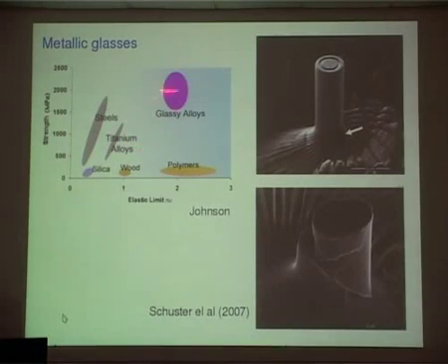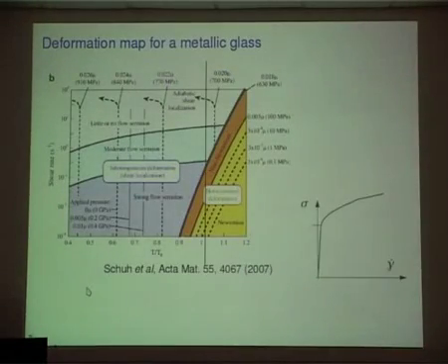So these metallic glasses, just to show you why they interest people, essentially they are harder, they have higher strengths than steels and larger elastic limits. And their big problem, and here that's again a sample of metallic glass which is then compressed, is that they are brittle. And the one thing we want to understand is the emergence of shear localization that we see here. Essentially, you compress a system, and the system will start to localize and crack along one band. And the question is how this happens. Okay, so that's the general idea, and I'll pass on this.